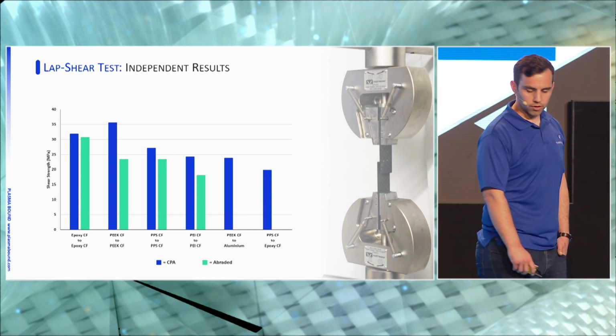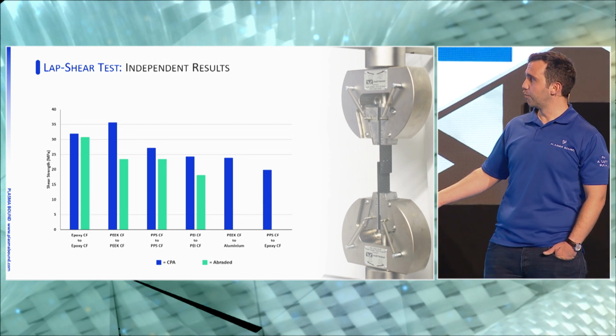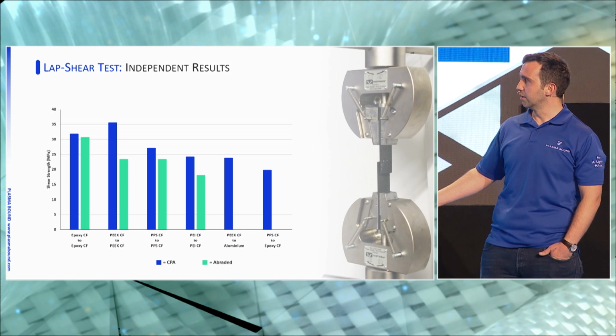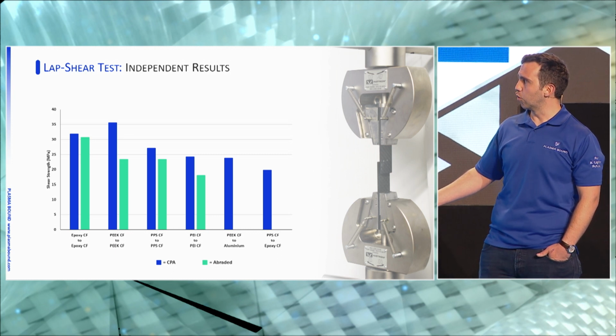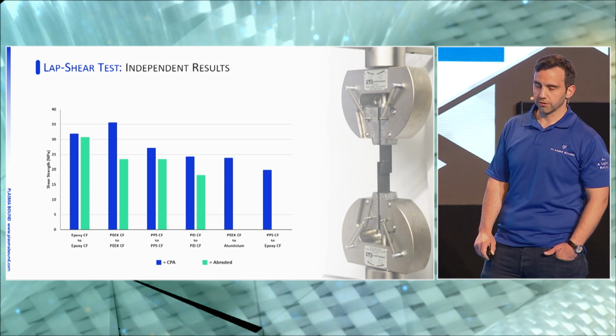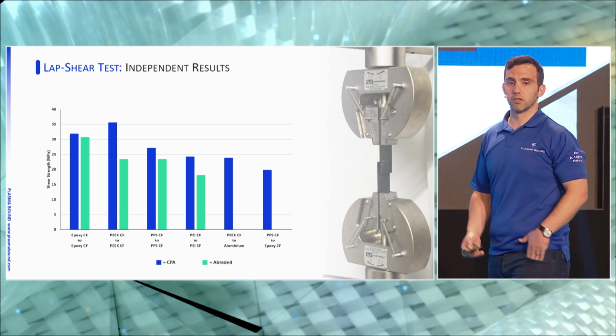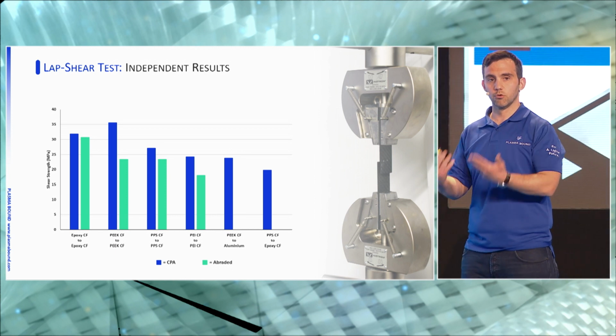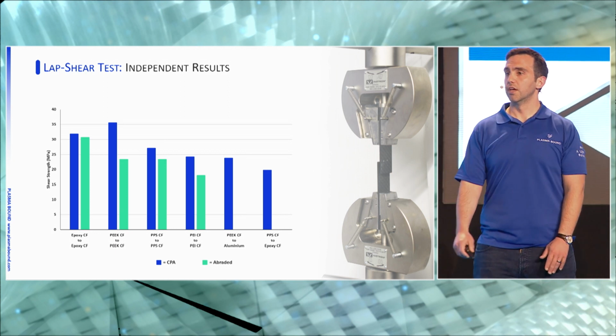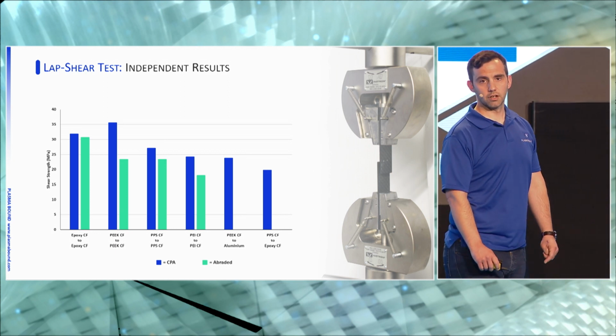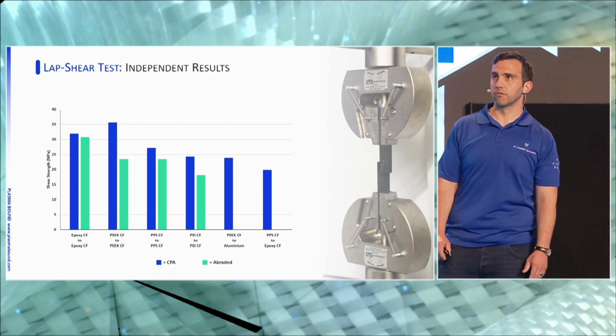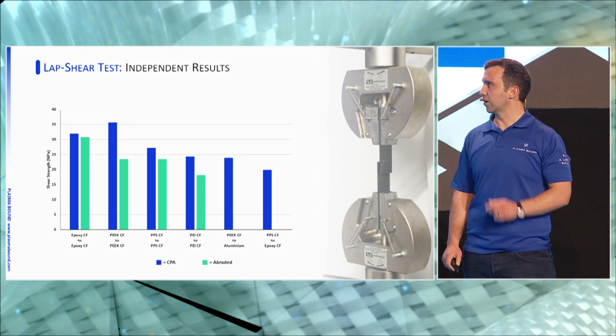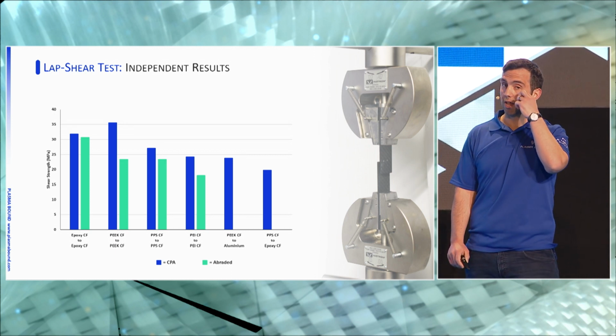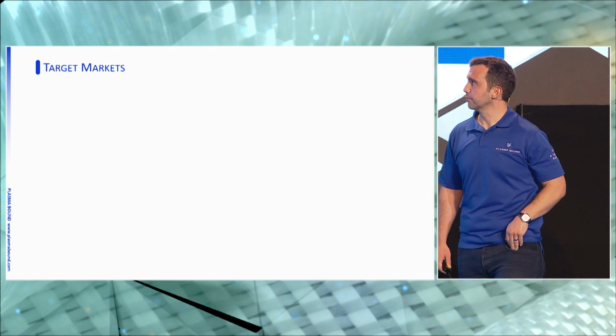And then the final one, which is PPS carbon fiber to epoxy, which is an interesting area because it's an overmold. Essentially, the PPS was treated, and then the epoxy was cured onto the surface of the PPS. So we exposed the fiber structure, and then they cured the epoxy onto that surface. It caused substrate failure of the epoxy, the consolidated epoxy afterwards, and reached the maximum interlaminar shear of the epoxy.